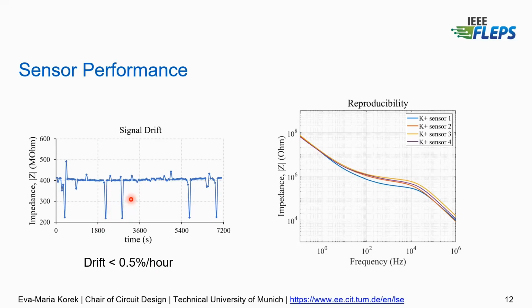Then we also manufactured 4 different potassium sensors on 4 different days, and we measured them on different days. And the reproducibility is pretty good, especially at the very low frequencies again. So the error is less than 7%, which is similar to the accuracy of the sensor.